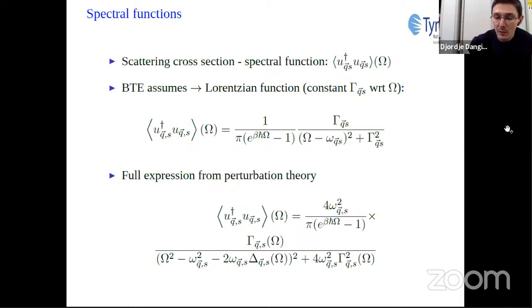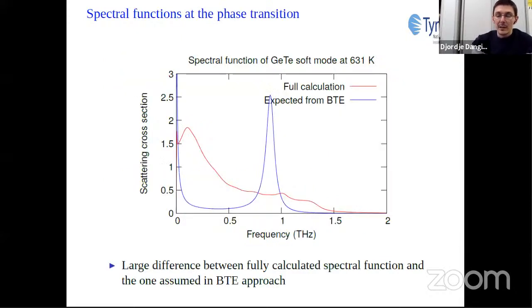So how do these two expressions compare for highly anharmonic materials? I'm showing that on the graph here. I calculated the phonon spectral function fully from first principles and the perturbation theory, and I'm showing that in the red line here, while the blue line shows what the Boltzmann transport equation thinks the phonon spectral function looks like. And we can obviously immediately notice the stark difference between these two lines.